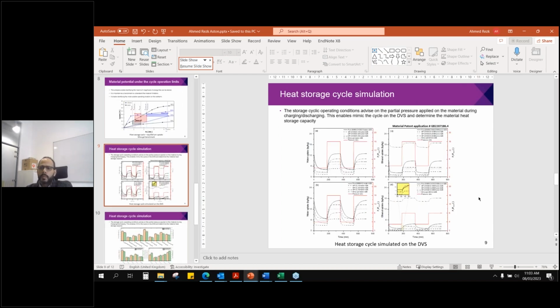So now we move to mimic the cycle operation actually by changing the partial pressure in the device to represent the operating temperature during the absorption and desorption. So we change the partial pressure to represent this. So here actually we have high partial pressure. It means that we have discharging. So we have low partial pressure, we have charging, right? So while we charge, we dry up the material. While we discharge, we humidify the material or apply the sorbent to the sorbate.